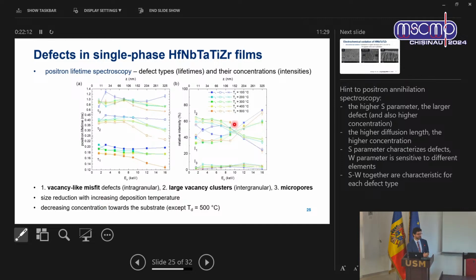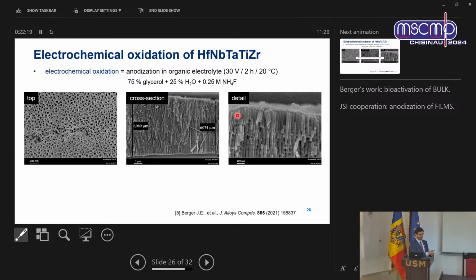Now, at this point, I would like to introduce another way how to oxidize these films, because the first goal, to produce the single-phase high entropy film, was accomplished, but still we would like to also do some research on these high entropy oxide films. And as you've seen, we didn't achieve them yet. Increasing the temperature, direct oxidation, doesn't lead to good results, but you can do it at room temperature using electrochemical oxidation.